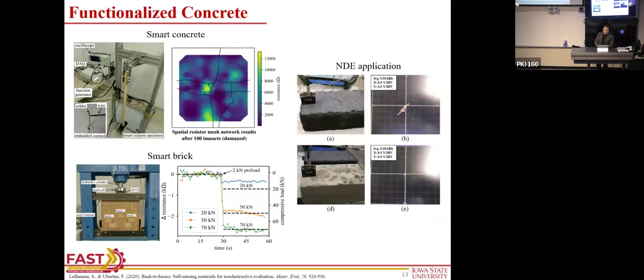We made a slab of concrete that was a resistor, and we were able to track cracks that occur in the concrete. That's a hammer that we use to hit that slab 100 times. Measure the crack, measure the flow of the electrical current in the slab, and then we're able to look at where the cracks could be.